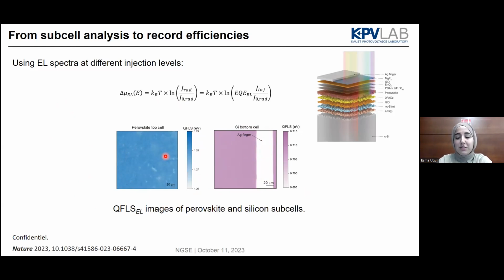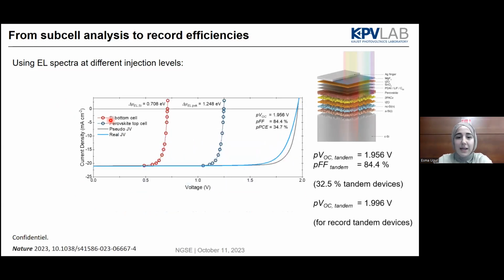That is a different story. And with the different injection levels, you can mimic the JV for this perovskite. So this is the 32.5% tandem device that we have. And actually, we can get the fill factor up to 84%. That means that if we don't have any serious resistance issues, the potential of this device is actually quite high.